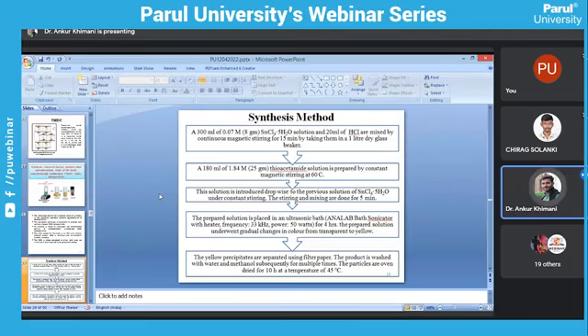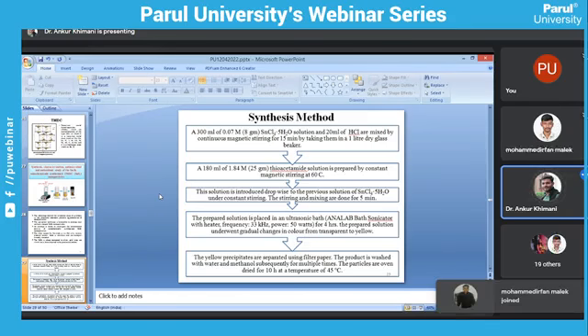The yellow precipitates are separated using filter paper. The product is washed with water and methanol subsequently, multiple times. The particles are oven dried for 10 hours at a temperature of 45 degrees Celsius.